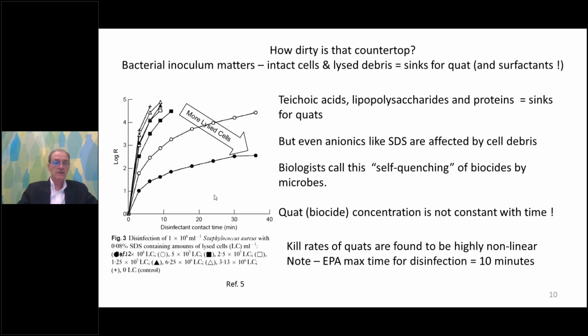And so what we have here on the left is the log reduction. That is the logarithm of the number of bacteria that we've killed as a function of time for using SDS at various times. What we see is as we add more cellular debris, more lysed cells to the dispersion that the SDS is in, the log reduction slows down and is decreased. Biologists call this self-quenching. The microbes are actually quenching in continuous time. They're quenching the activity of the biocide. And so what that amounts to is biocide concentrations, as you use them, is not constant. This gives rise to really highly nonlinear kill curves, as we're going to see.